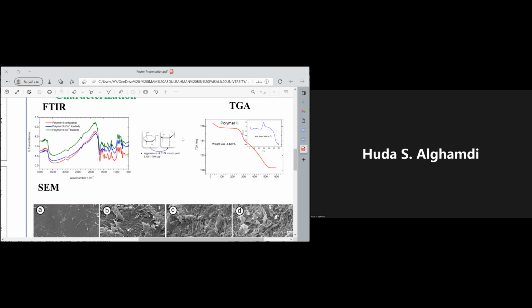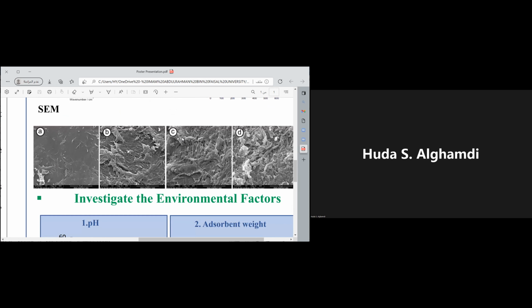Then the XRD also gave a pattern exhibiting the change in the materials with lower intensities. And the surface morphology for the SEM showed alteration in the surface. As you can see, A corresponds to chitosan itself. B, C, and D have more roughness and channels in the surface. So this is the difference. And also we took another picture after adsorption. This roughness is gone, and we saw a very smooth surface, which indicates that the adsorption process happened. Okay. This is for the characterization.